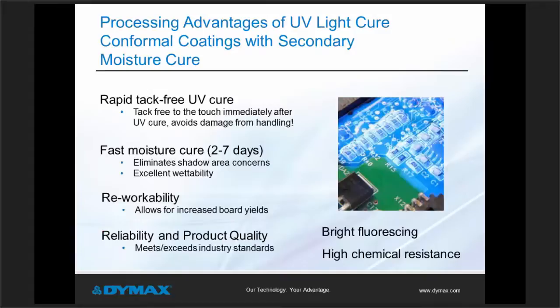So, in particular, comparing UV light curable materials with a secondary moisture cure to other chemistries, there are a lot of advantages that can lead to increasing process efficiencies. The actual advantages do depend on the particular material offered by each of the coating manufacturers, yet currently commercial materials can offer things like immediate tack-free curing in seconds, fast curing under ambient conditions, and this can happen in as little as 2 or 3 days,